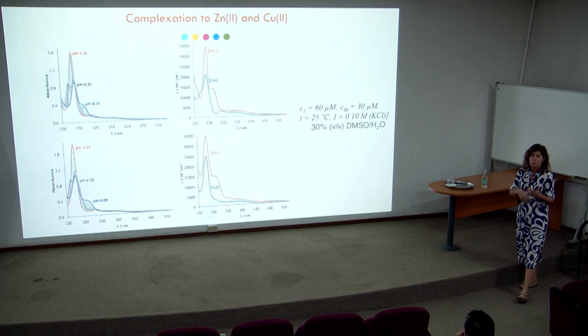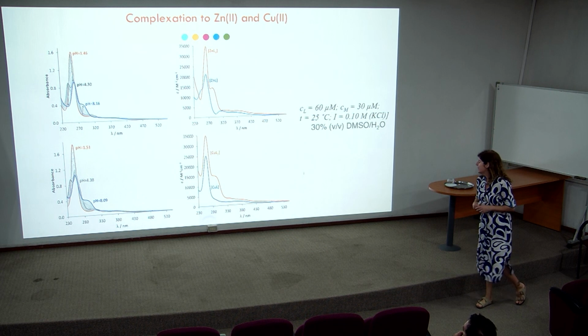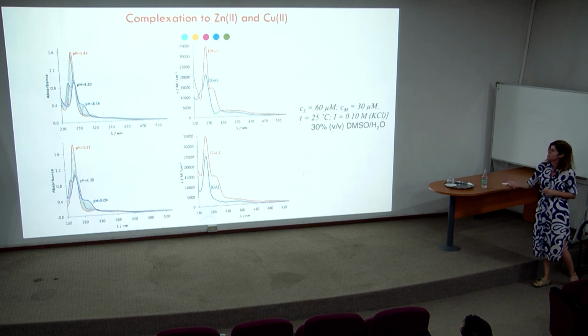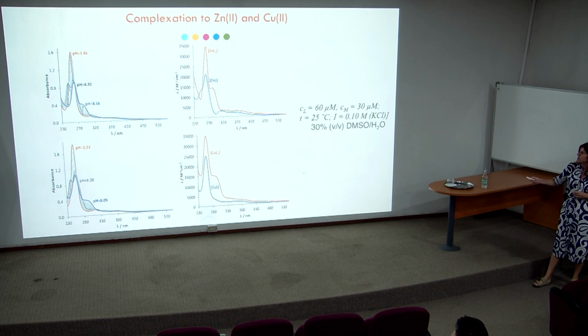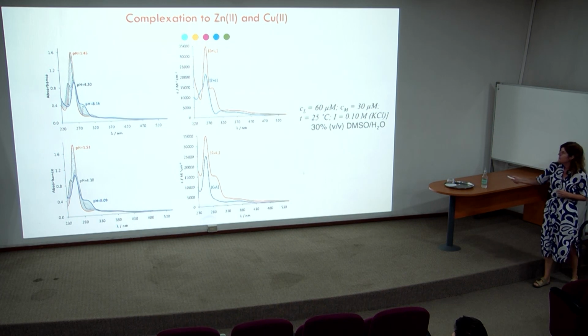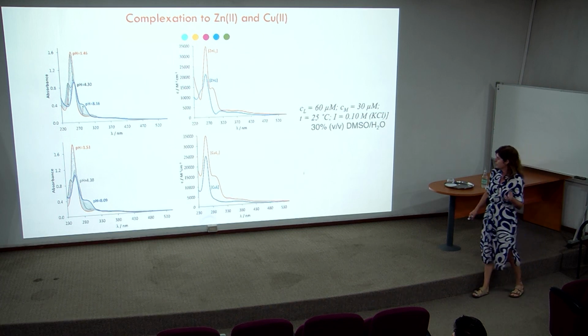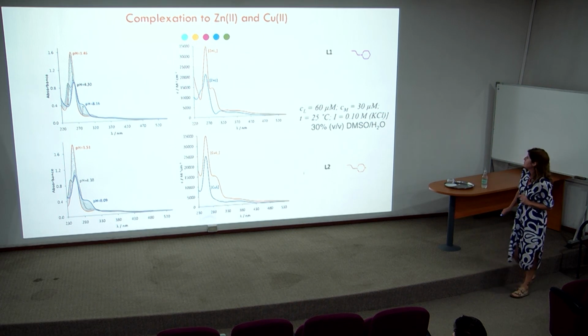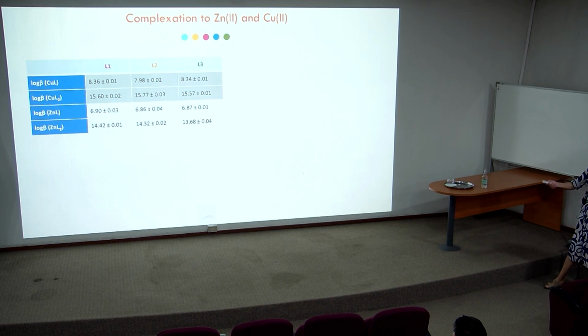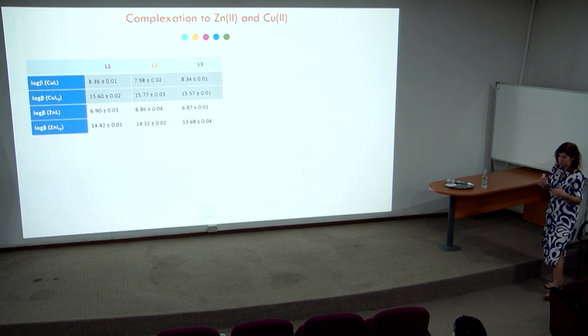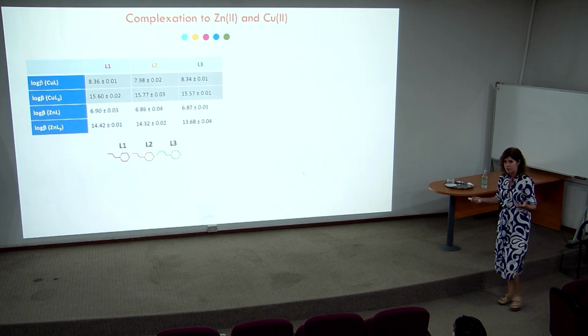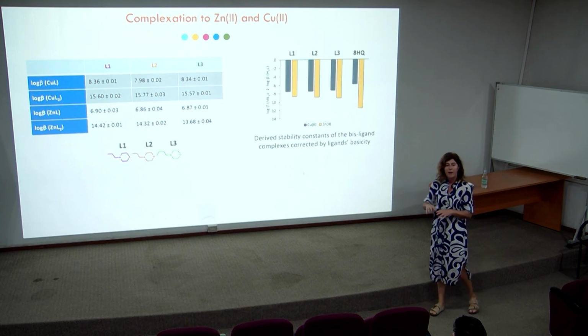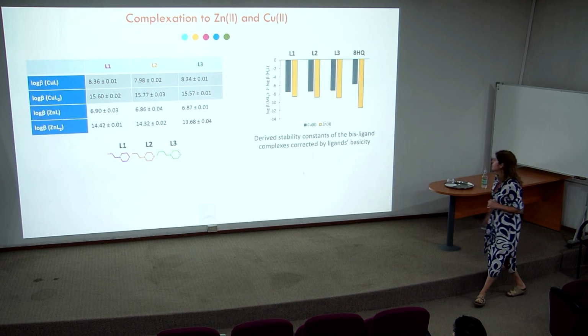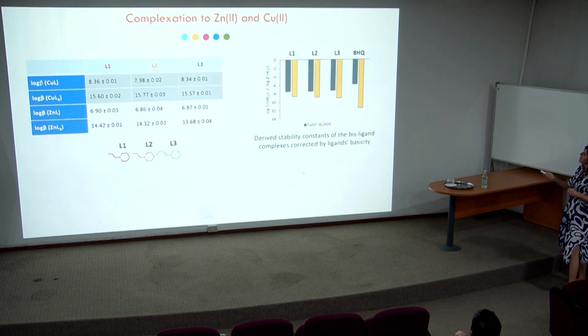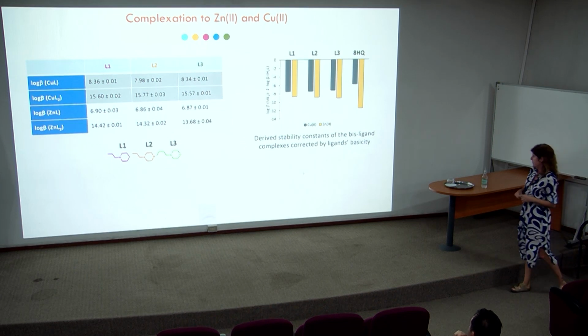So next we study the complexation by aqueous speciation. You can see here the spectra that were measured for one of the zinc systems and the spectra for copper, and we assigned two different 1:1 and 1:2 species. Here we have the overall stability constants. Of course, we wanted to compare these constants with 8-hydroxyquinoline to see the impact of having an additional binder. And you have here a table that shows derived stability constants for the bis complexes corrected by ligand basicity.